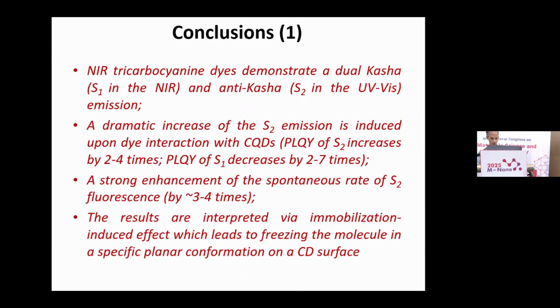As a conclusion concerning the first part of my presentation, I showed you that specific infrared dyes can produce dual Kasha and Anti-Kasha emission. We can enhance Anti-Kasha emission by interaction with carbon nanoparticles by a factor of 2 to 4, and simultaneously the quantum yield of the Kasha emission decreases by a factor of 2 to 7. The Anti-Kasha emission enhancement is realized due to the enhancement of the spontaneous rate of fluorescence by a factor of 3 to 4. This enhancement is explained by an immobilization-induced effect, which leads to freezing the molecule in a specific planar conformation on the nanoparticle surface.